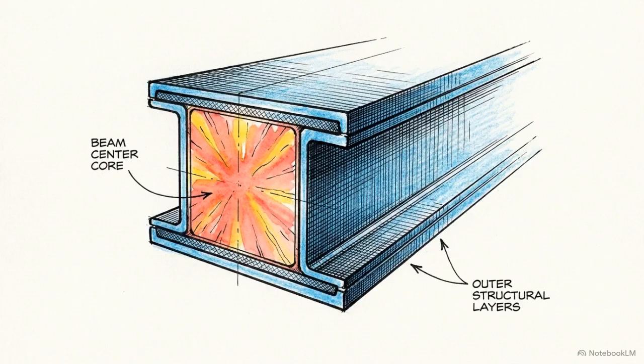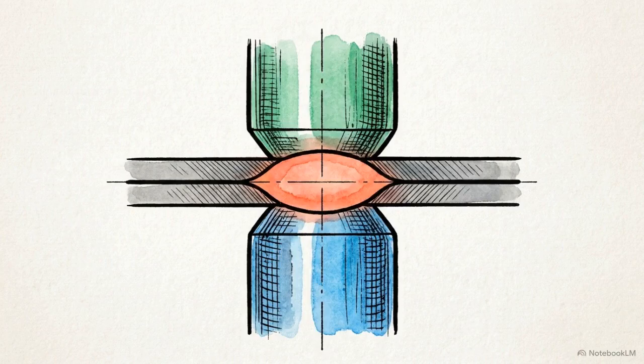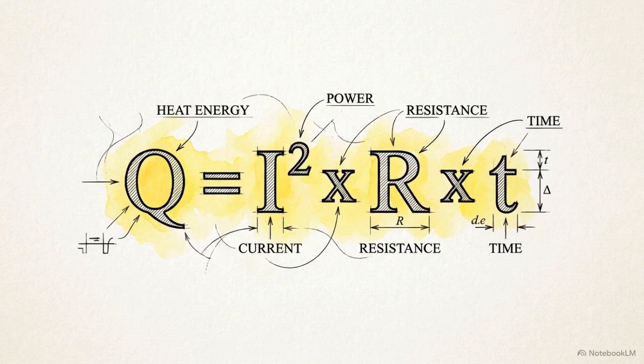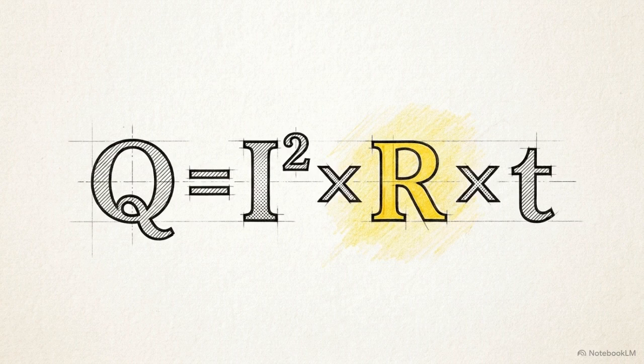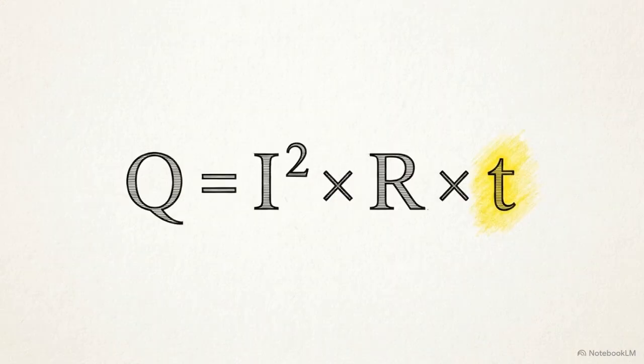This physical bottleneck is an engineering advantage. It forces the highest heat generation to occur exactly where the two sheets meet, rather than burning the outer surfaces contacting the copper electrodes. We calculate the exact energy of this localized melt using the resistive heating relationship. The formula is Q equals I squared times R times T. Here, R represents the effective resistance at the faying surface, and T is the total weld time, which is usually measured in exact milliseconds or cycles of the alternating current power supply.